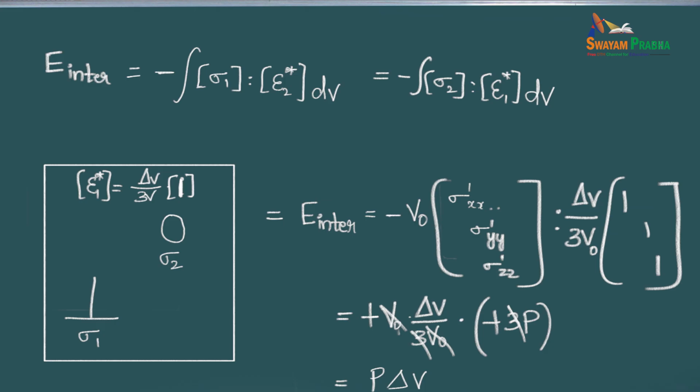For a spherical object like this, we know the stress field. It's called the Eshelby inclusion problem. So I know the stress field created by a vacancy. I could have used the same thing, but looking at the integral of the stress created by the vacancy on the cut surface of the dislocation. That would have given me exactly the same result, except that it might be less practical, although there's another expression for dislocations. But you see the idea. You can choose which one is the most convenient depending on your problem.